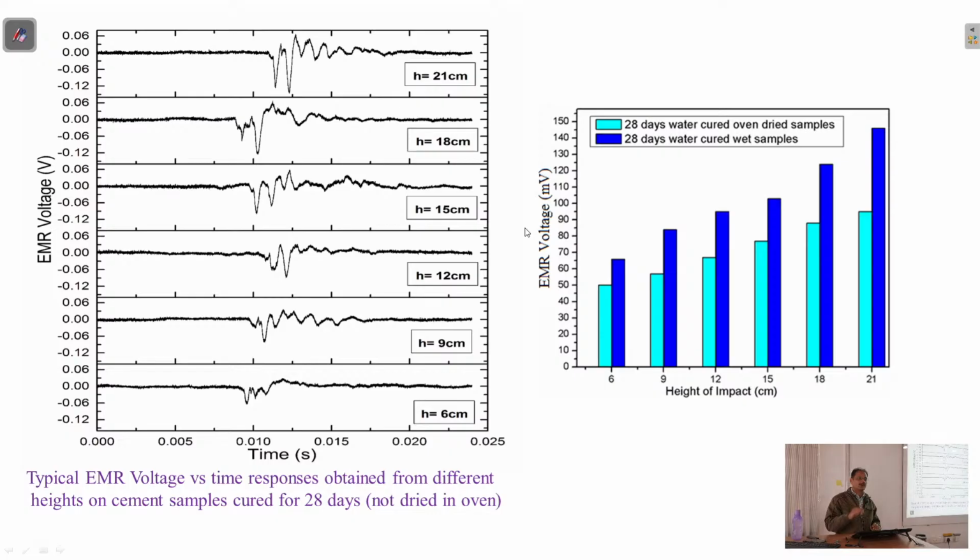The order here is less by 10 to the power 3, so you have to divide whatever we achieve with PZT by 10 to the power 3, then we are somewhere near the actual values from this cement. But all the same, it's a happy finding, because cement is the most common structural material, and at least some signal we are directly obtaining from the cement.